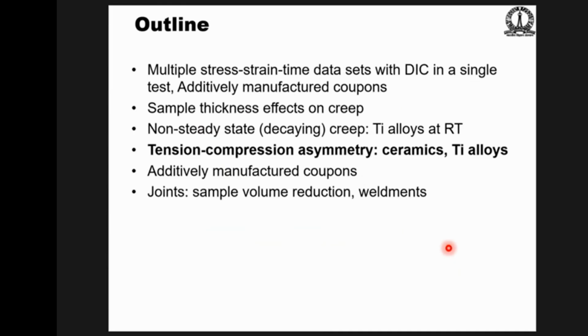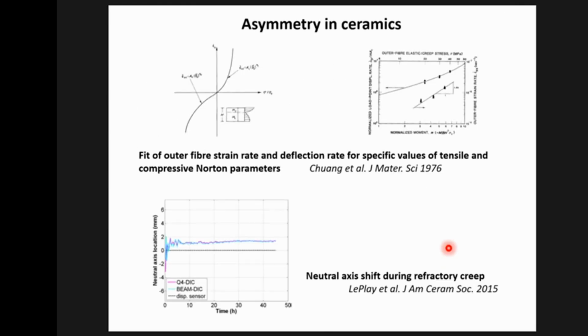Now let's come to tension compression asymmetry. This is an outstanding problem. It's been dealt with in ceramics, concrete, many materials which creep over geological timescales, but which have inherent porosity. They are by definition almost tension compression asymmetric. And so people have grappled with this problem, and they've recognized, this is from some work on refractories. You'll notice that the original midpoint of the beam is here, but the neutral axis has shifted to one side after a long period of refractory deformation.